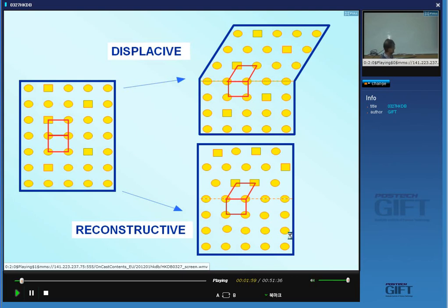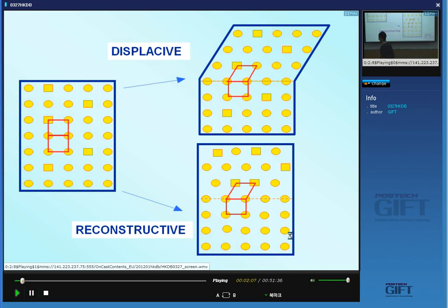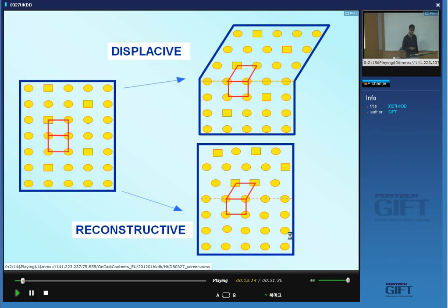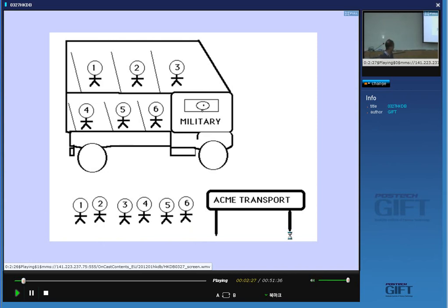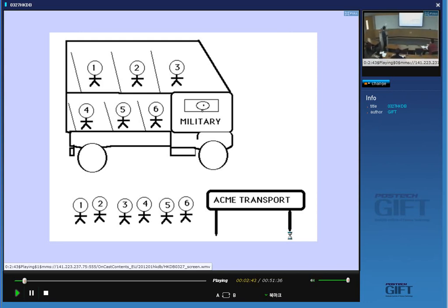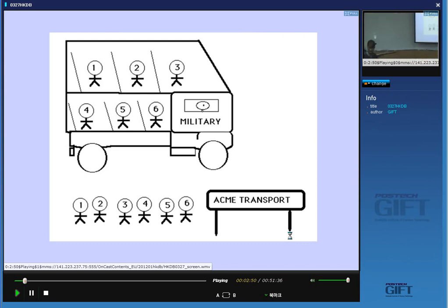You can imagine it happening in two steps: first we have a displacive transformation, then diffusion which eliminates any shape deformation. So these are the two mechanisms. The displacive transformation is an extremely disciplined transformation whereas in reconstructive the atoms move in a random manner. Supposing we imagine the displacive transformation as a queue of soldiers who are waiting at a stop where military transport is going to take them. When they board the bus they board in a highly disciplined manner so their near neighbours are still the same — this is called a military transformation.